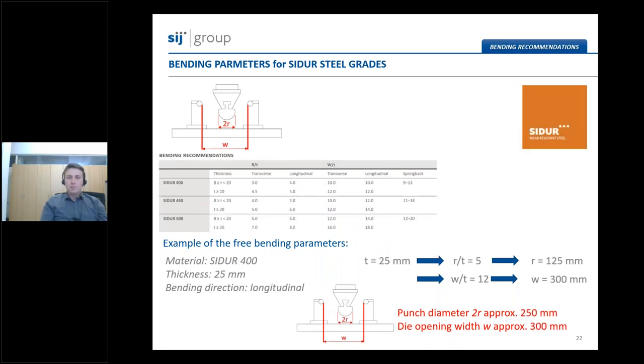As it was already mentioned before, you will also find all the necessary factors for punch radius and die opening width in our technical data sheets. So in this slide, I just made one example of bending SIDUR 400 grade with the thickness of 25 millimeters in the longitudinal direction. And the calculation is, I think, clearly presented.